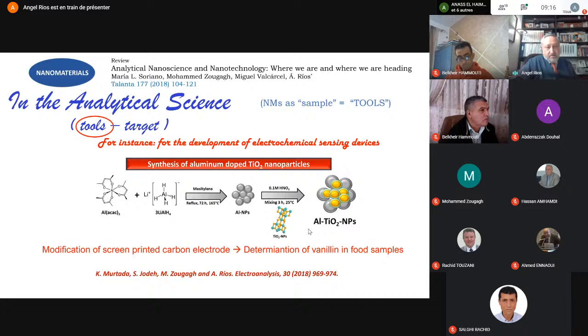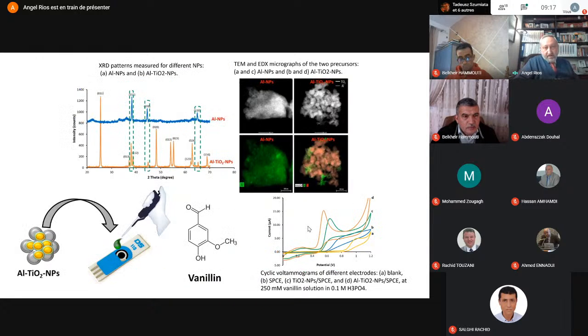And in this case, for instance, for the development of an electrochemical sensing device, for the modification of screen printed carbon electrode and the determination of vanillin in food samples, by using the synthesis, of course, of aluminum doped titanium dioxide nanoparticles in order to modify the screen printed carbon electrode. Of course, it's important to have a good characterization of this nanomaterial in order to have reproducibility between different batches.